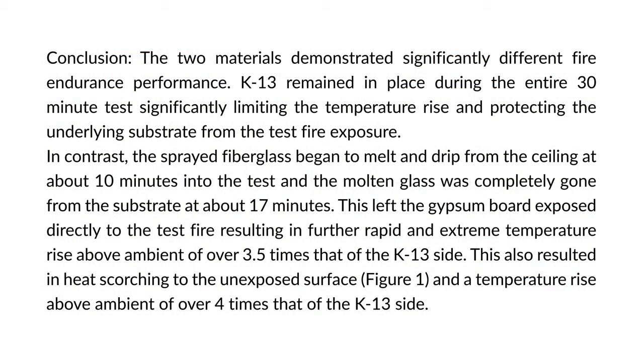Conclusion: the two materials demonstrated significantly different fire endurance performance. K-13 remained in place during the entire 30-minute test, significantly limiting the temperature rise and protecting the underlying substrate from the test fire exposure. In contrast, the sprayed fiberglass began to melt and drip from the ceiling at about 10 minutes into the test, and the molten glass was completely gone from the substrate at about 17 minutes.